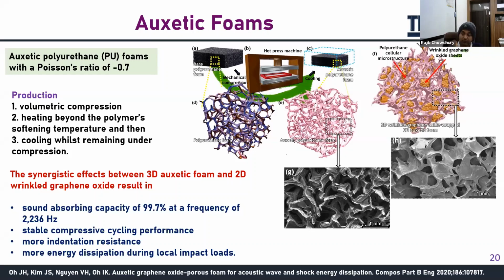Now, what would happen? Your process technique has to be developed in this way, so that it involves volumetric compression, heating beyond the polymer softening, because it is a polymer. So the polymer softening temperature is to be maintained in this particular fashion. And then the cooling whilst it remains under the compression. So besides PU foam, the polyurethane foams, other polyethylene foams were transformed into the reentrant microstructure through thermomechanical processing. So the processing technologies are also going to emerge very rapidly to achieve this kind of unusual